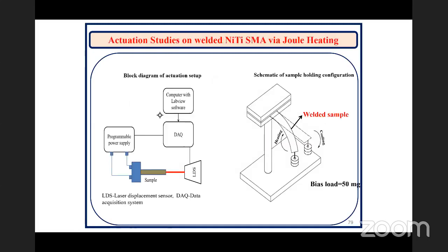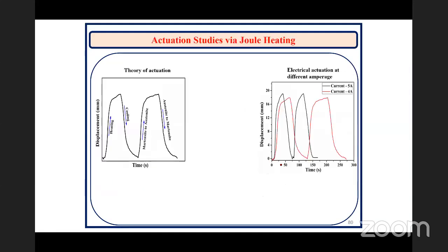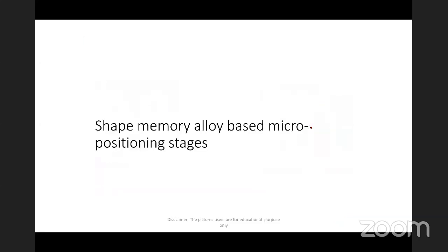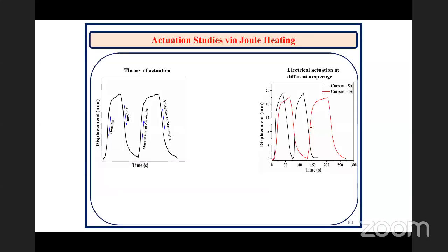In fact, we went for a complete life cycle analysis of these welded structures. We kept a system over here and a weight arrangement on top of it. With this weight arrangement, we were continuously loading the unit, and by applying heat to it, we were trying to continuously study the life cycle behavior coming out of it. Here you see the life cycle behavior, where there is alternate heating and cooling, and there is a martensite and an austenite phase which is capable enough to study the characteristics too. So these are some of the challenges which we have addressed overall.